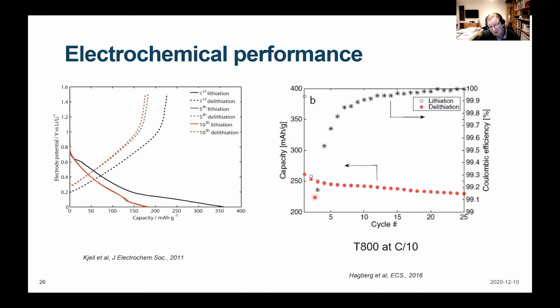And this is also important then, not only to have the capacity for the battery, but also we need to know how many cycles this battery will work. You know, if you buy a cell phone, maybe after 3 years, it doesn't stay charged very long. And this is because the capacity is reduced with time. And this is a measurement where we see how big retention we have in the battery. You can see this should approach 100%. If we are below 99%, of course, then this battery will decay very, very quickly. And this is showing quite promising results for this particular carbon fiber.